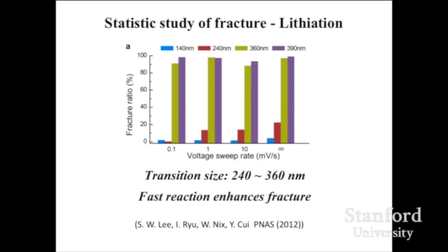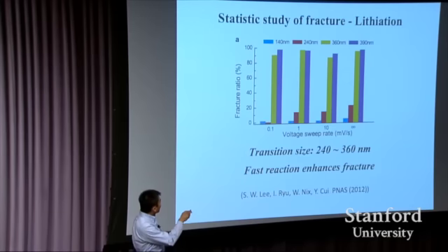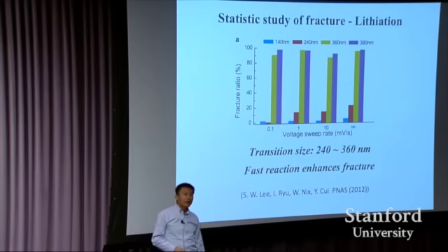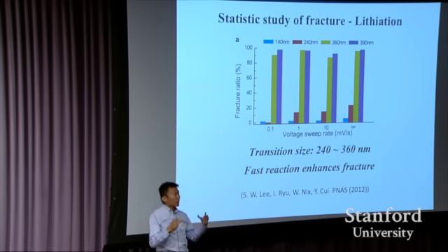And then you also use different charging speed to charge your batteries. The faster you charge, this 240 nanometer, the breaking ratio is increased. Now the thinking is, I want my battery to be charged very, very fast. Can I do that? The answer is probably not. If you do it faster, you break your battery's materials. So if you want to go to whatever, like 8 minutes, 10 minutes charging for electric cars, don't try that. So you probably break your batteries.